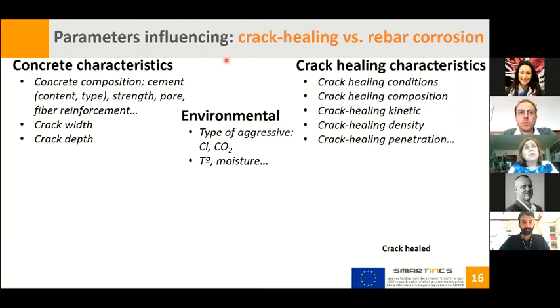What are the parameters that could be influencing the crack healing versus the rebar corrosion? We have concrete characteristics that influence the performance: the concrete composition, the cement, the concrete type, the strength, the pore structure, the fiber reinforcement of the concrete. Of course, the crack width and the crack depth. We have the environmental influence. The type of aggressive agent is not the same if we are in a chloride environment or in a carbonation environment, or the combination of both. The temperature, of course, can influence, and the moisture significantly in the case of corrosion.